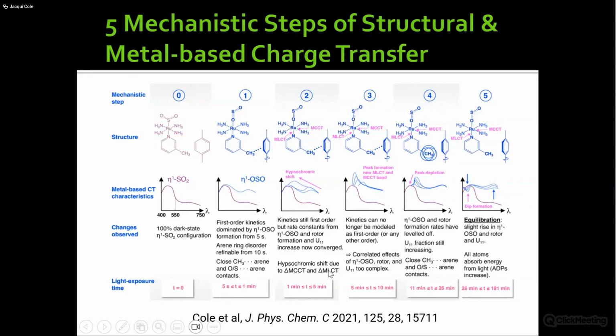And you see this hypsochromic shift, right? And given what's in the literature from other ruthenium-based coordination complexes, not so much with single crystals, but nonetheless, we assign these changes optically to changes in metal-centered charge transfer and metal-ligand charge transfer. And then it gets a bit more complicated, with this peak forming that you saw in the previous slide.